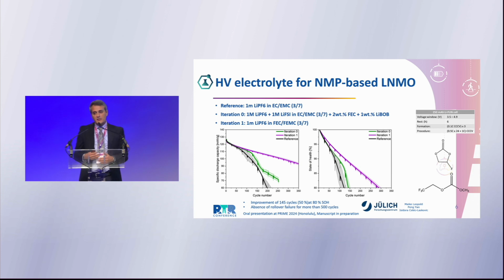So we start from a market-available reference, which is the LiPF6. And in iteration 0, we have already modified this reference for better performance and increased safety by adding some extra elements into the electrolyte formulation. We have further refined this recipe to achieve what you see on the slide, the iteration 1 reference electrolyte, which is the pink curve that can provide much better capacity and cyclability compared to the iteration 0 reference.